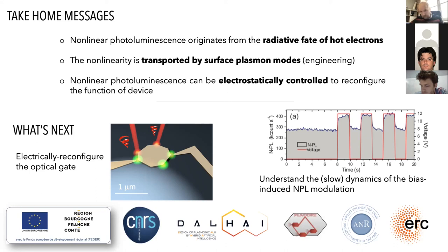So if you have a larger gap, you apply more bias, basically, and you see the same effects. Of course, the smaller, the better. For this optical excitation, we are usually working with gaps that are in the 30 to 50 nanometer range. So we are far off tunneling transport. However, and I thank you for the question, because this is basically part of the story.